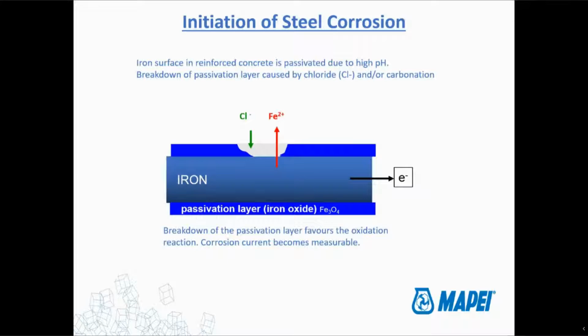But once the corrosion starts happening, now you have chlorides that are able to actually start reacting with the iron in the reinforcing steel. The passivation layer gets breached, and those chlorides really start to react with iron, and they start forming what we call iron oxides. Iron oxide is the technical term for rust that you're more familiar with. So that's the orange, rust color that you see leaking out of the concrete. And of course, the rust that you see on the reinforcement steel. That's from those irons reacting with oxygen. And again, we'll go through this in more detail in the next few slides, but just as an introduction to what's happening.